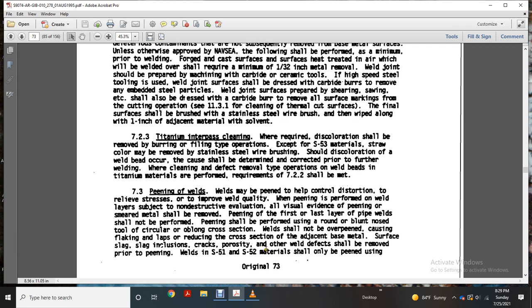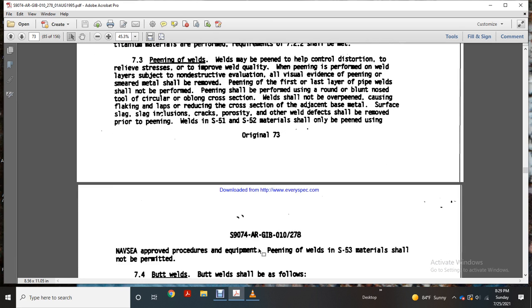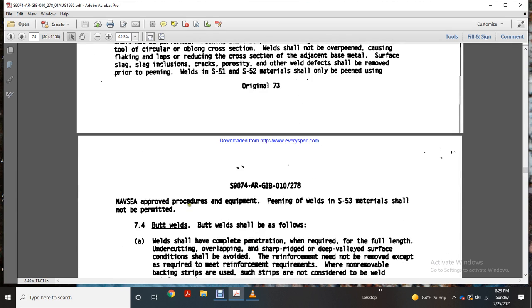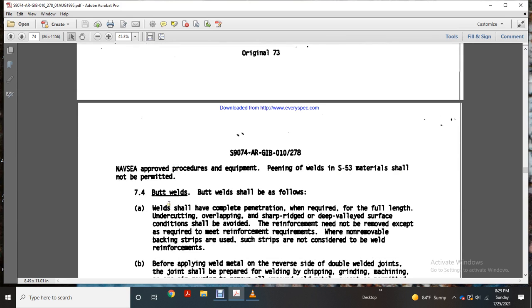Welds in S51 and S52 materials shall only be peened when Navsea system command approved. Peening equipment shall not be permitted on welds of S53 material, but welds shall be made as follows. The weld shall be completed with the required penetration and full length, avoiding undercutting, overlapping, sharp ridges, and deep valleys. Such surface conditions shall be avoided. The reinforcement need not be removed except as required to meet the reinforcement requirements. Nonremovable backing strips are not considered to be welded.